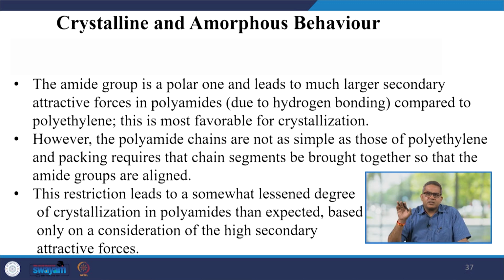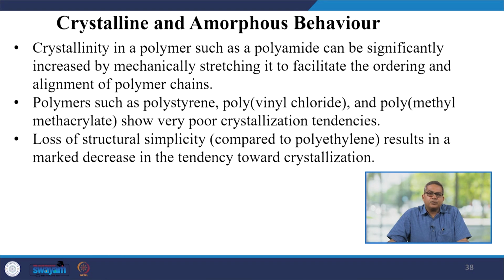The polyamide chains are not as simple as polyethylene, and packing requires that the chain segments be brought together so that the amide groups are aligned. This restriction leads to a somewhat lesser degree of crystallization in the polyamides than expected based only on a consideration of high secondary attractive forces. The crystallinity in a polymer like polyamide can be significantly increased by mechanically stretching it to facilitate the ordering and alignment of the polymer chains.